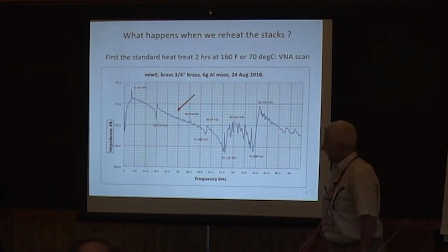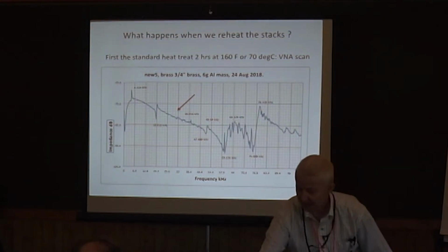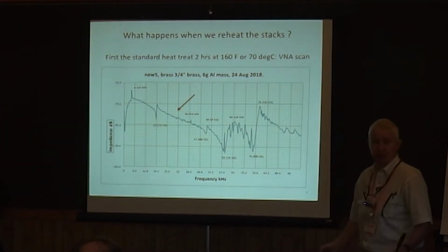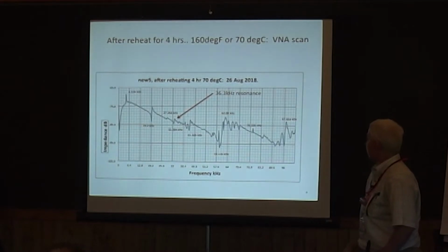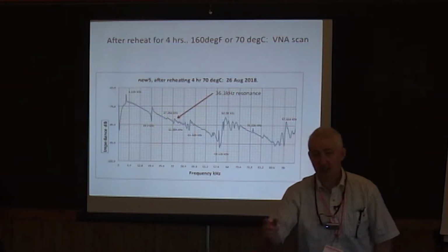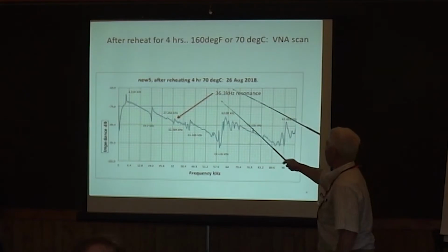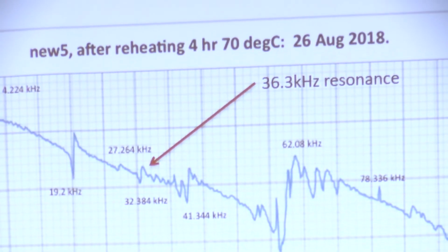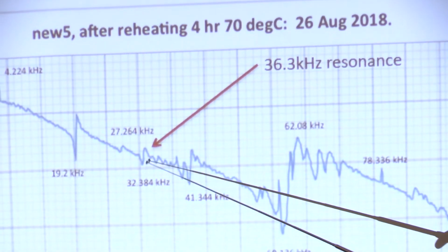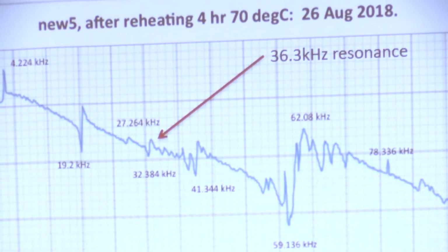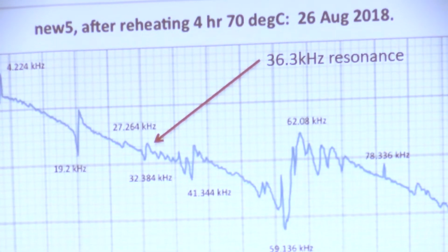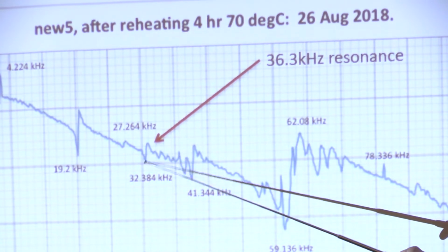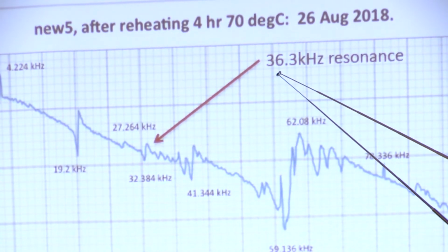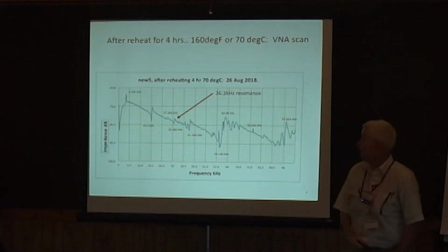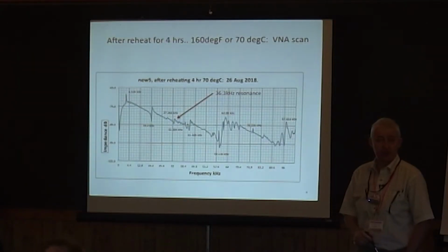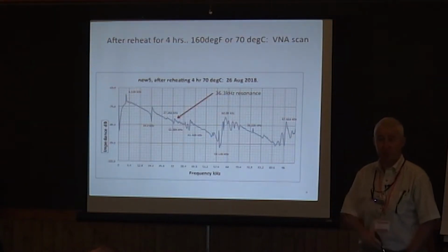So we thought, well, why not try to reheat this thing and see if we can get it to do so. We thought the curing of the epoxy was the problem. And so I reheated it at Jose's advice for 4 hours at that same temperature, 160 degrees Fahrenheit. And now we've got this little bit of a blip going on at 32.4-ish kilohertz. We don't actually run at the resonance, we run slightly higher. So that's actually going to give us a thrust at around 36.3 kilohertz, which is very similar to the demo device that we sent to you guys.